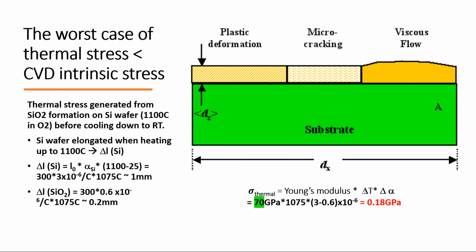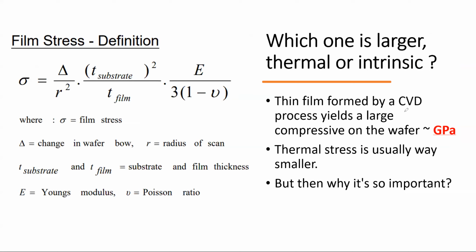That's the Young's modulus times the temperature difference times the thermal expansion coefficient difference. So you put this together and you figure, wow, it's only 0.18 gigapascal. It's reasonably big, don't get me wrong, it's still big. But if you compare it with the thin film stress from a CVD process that you measure in your fab, you can easily see gigapascal in the stress measurement. So that's the reason I said thermal stress is usually way smaller compared with the intrinsic stress induced by the bonding.